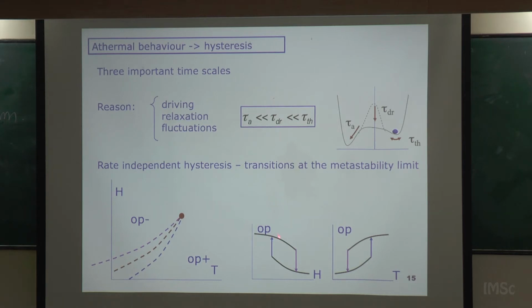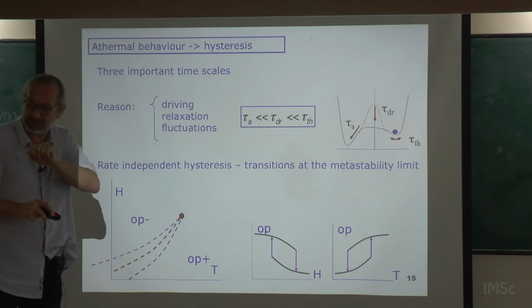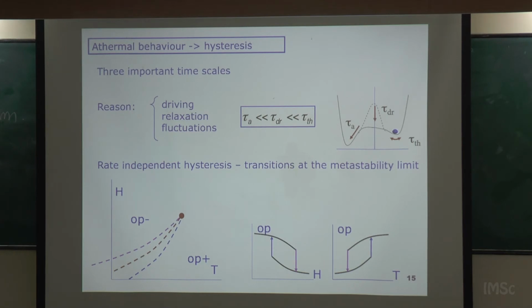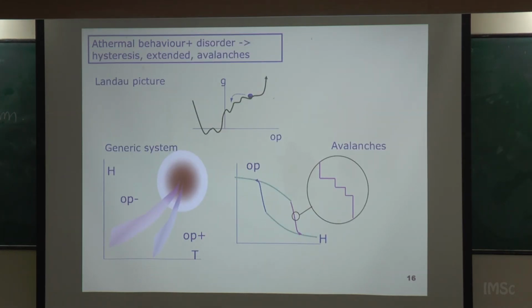Why the transition doesn't occur at one point, but you have to change the driving, keep going, in order for the transition to proceed. And for that, we need a new ingredient, which is disorder. Now, this is more difficult to do, but there are microscopic models like the Ising model that you were mentioning. When you add disorder, you can solve that really well, the random field Ising model it is called, you put some randomness there. But what you get is something which, like a cartoon, can be described here. Okay, this is a cartoon of what is happening. The idea is that when you put disorder, instead of having only two wells that you jump from one to the other, you generate many, many, many intermediate wells.